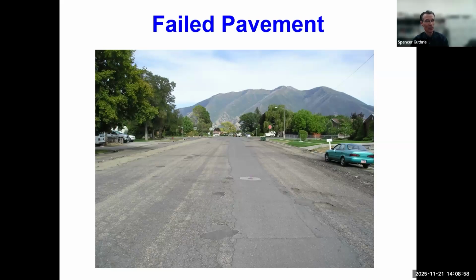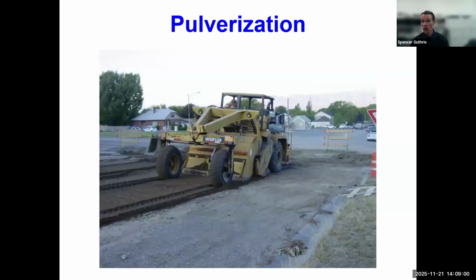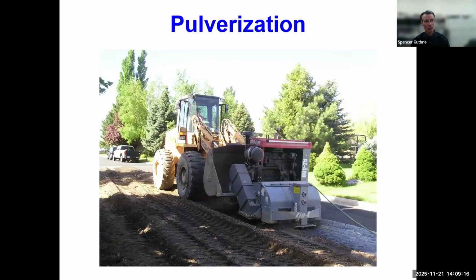So here's the failed pavement, and this is called a reclaimer, a large machine with a rotating drum between the front and rear axles that with a lot of horsepower can pulverize the asphalt and mix it with a portion of the underlying base material. After the material has been pulverized, we can reshape it. If we don't have access to a large machine, we can also use a smaller asphalt zipper. Perhaps some of you have seen these on job sites.